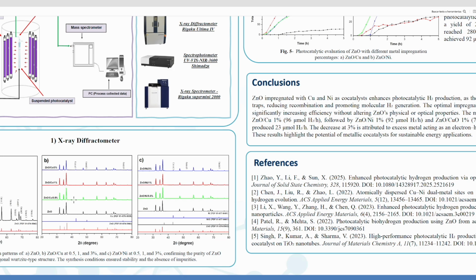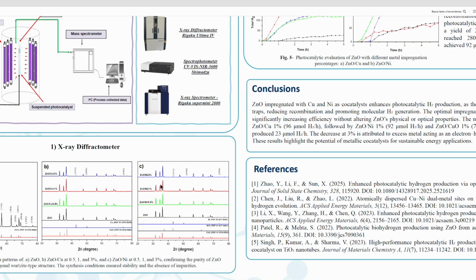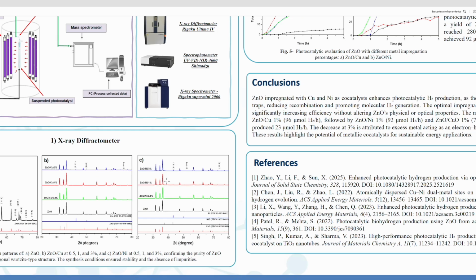Subsequently, the smaller percentages are due to instrumental error and the amount impregnated. Well, the diffractometer is a characterization method that doesn't help us to actually visualize it. But in fact, the equipment did detect the card, but no peaks are visible. The same thing happened with nickel at 3%. We were able to obtain the Miller indices, but at 1%, those peaks can no longer be seen, and the same goes for 0.5%. The trend is that the greater the amount of metal, the more visible these peaks are.